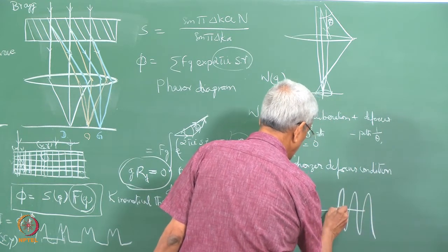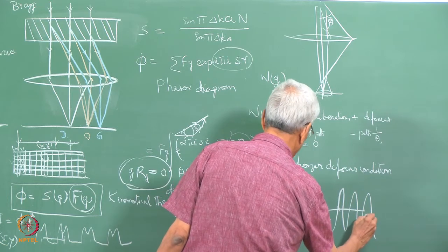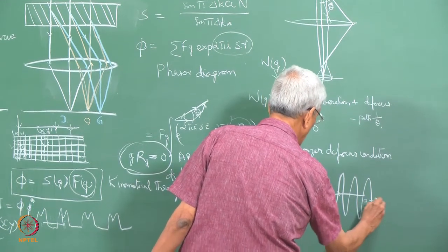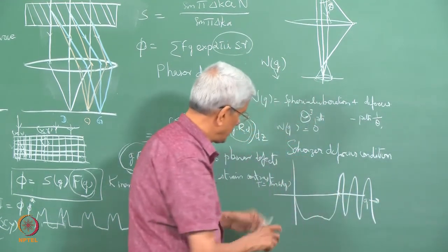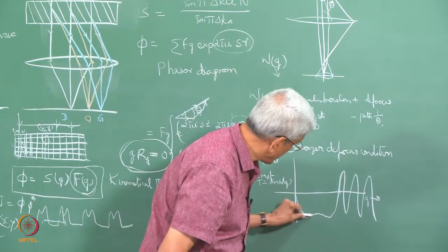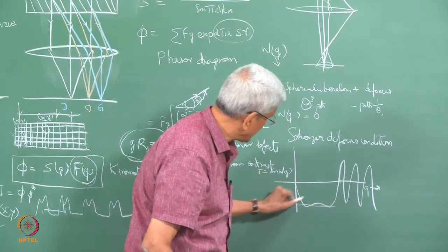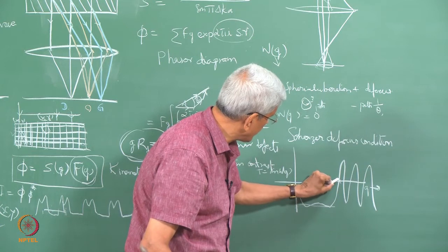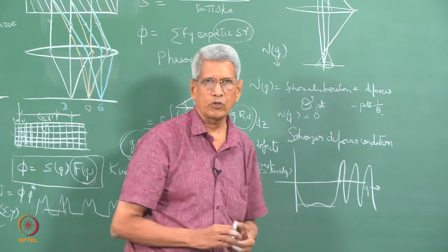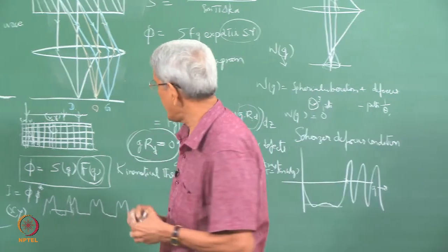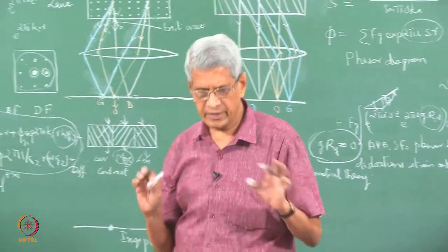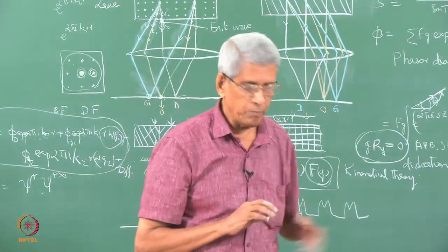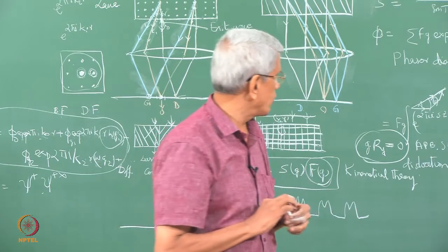So, with respect to g, what is the distance up to which this value turns out to be of uniform factor? That is called the Scherzer resolution also. These are all the factors which are very important in high resolution imaging.